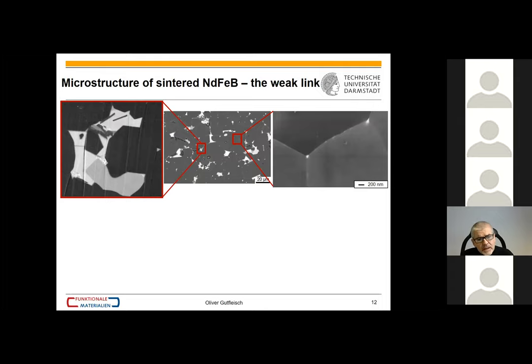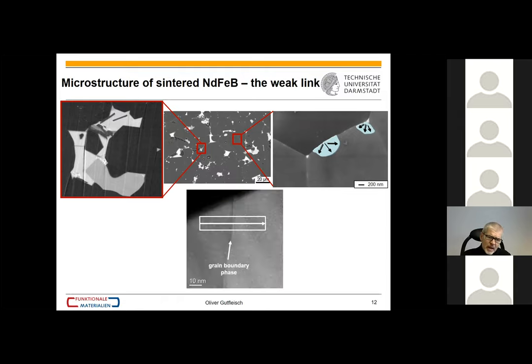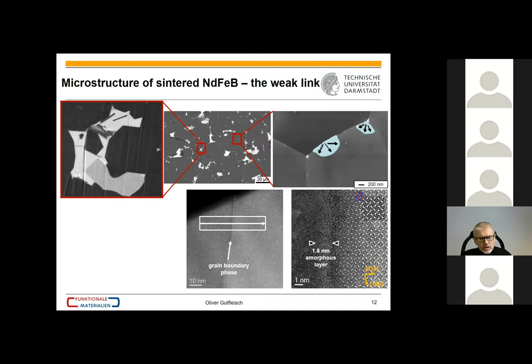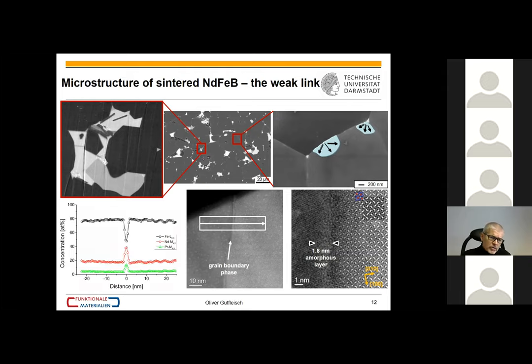Now it is all about understanding what is happening on the nanoscale at these interfaces, at the grain boundary. So you see here three different backscattered electron images, and we basically need to understand why magnetization reversal nucleates at such a point, at a triple junction, for example, or somewhere else, and how it then propagates. Dominique Givord developed beautiful models to describe this. And here now, going to higher resolution with transmission electron microscopy, we see more of the grain boundary phase. Even going further, we see a 1 to 2 nanometer amorphous layer here, bottom right. And we need to understand the nanochemistry, but we also need to understand the distortions, the defects around this grain boundary phase.